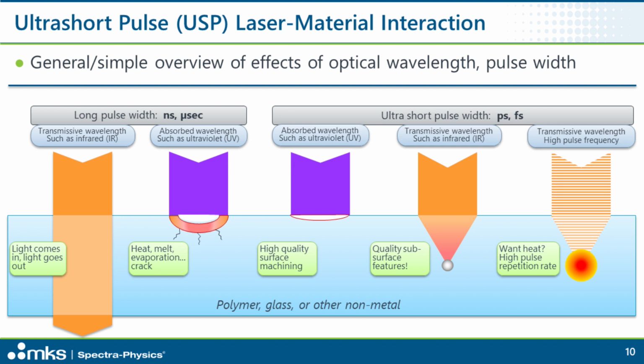Now, switching to shorter pulse widths in the pico and femtosecond regime, if you have that same short wavelength, you get stronger absorption, even stronger with nonlinear effects, and you can get a clean, shallow removal region. And with the right process parameters, you can have a very low heat input and very high quality surface machining. Now, if we go to the transmissive wavelength, because of the very short pulse widths and the high intensities, you can focus that transmissive light and trigger nonlinear absorption phenomena. And this allows you to, at a location of your choosing, based on your focusing, create this absorption and coupling of energy to the material, and then you can get subsurface high quality features as well. So this was really one of the game changers that ultra-short pulse lasers, especially higher energy ultra-short pulse lasers, brought to the material processing world.